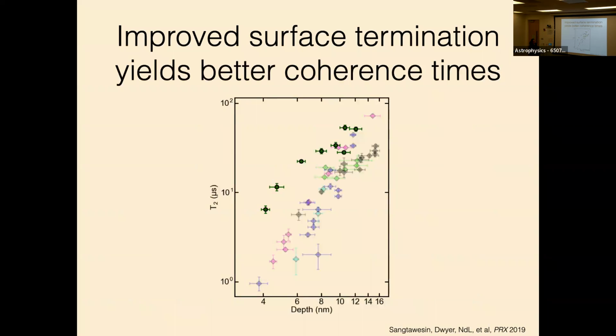Under these surfaces, we get much, much better coherence times. So these are all the data points that I showed you earlier. And then these dark green points are sort of a typical best surface where we're able to get extended coherence times by about a factor of 10. And actually, it turns out you can dynamically decouple to a couple hundred microseconds, even at these depths.